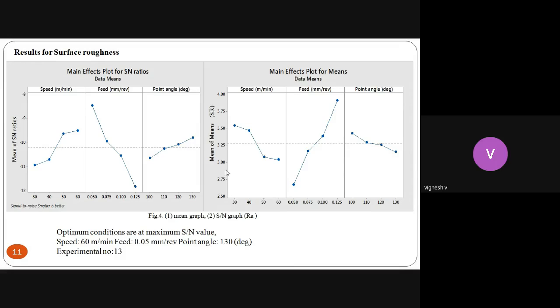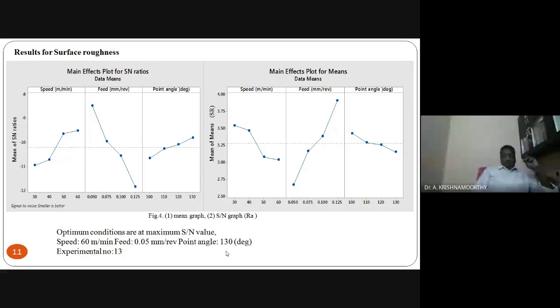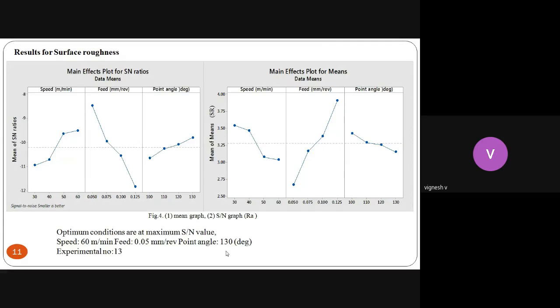So from that graph, we can identify that experimental number 13, that is speed 60, feed 0.05, and point angle 130 degree, is the maximum optimized condition to get a better surface roughness, right?